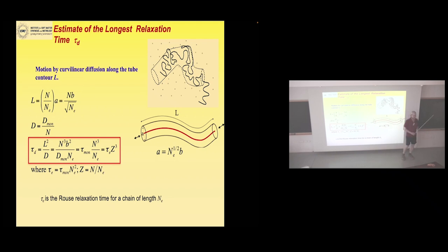But if you have, say, polyethylene compared to polymethyl methacrylate, same number of entanglements, polymethyl methacrylate has a really bulky thing going on, so it has a larger tau e. So for the same number of entanglements, it'll have a larger relaxation time. If you keep the entanglements the same, the time scale does change depending on the chemistry, because the chemistry determines tau e, determines Ne, and it determines the drag. So, yeah.